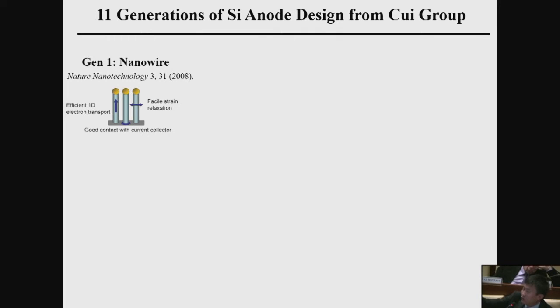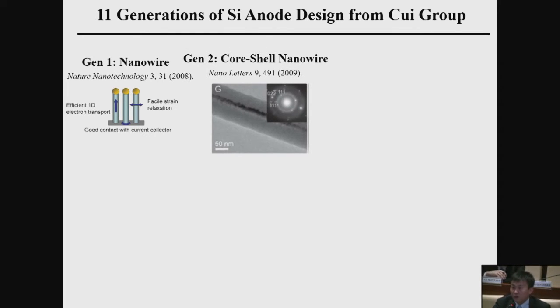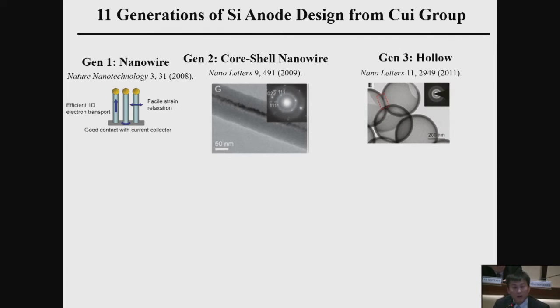By having this first generation of silicon nanowire, their diameters are small enough, so once the volume expansion happens, they can relax the strain to the outer surface, they don't break. So we showed nanotechnology is really powerful to help solve the problem in the battery field. And we move on, we have the second generation core-shell structure, having a stable core and a shell of silicon to store lithium, and then we produce the hollow structure, and the hollow structure can help relax the strain interiorly, inside, so to overcome the breaking problem better.